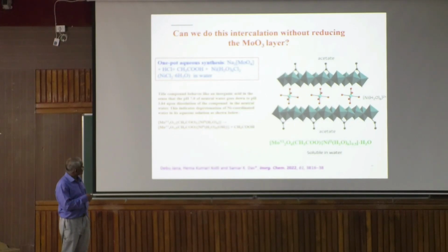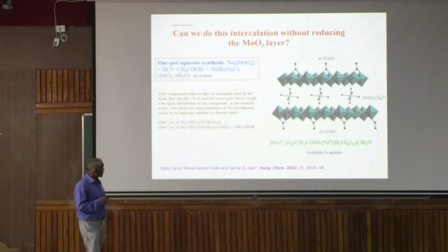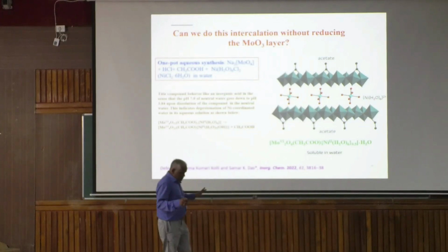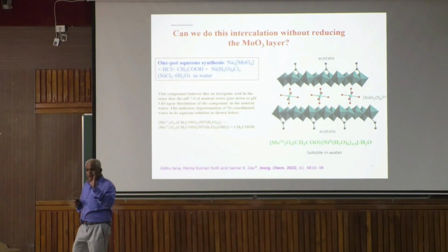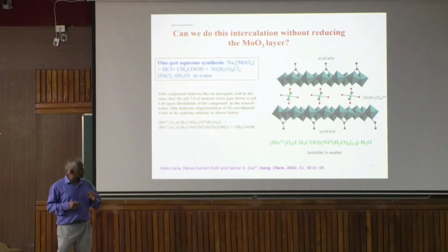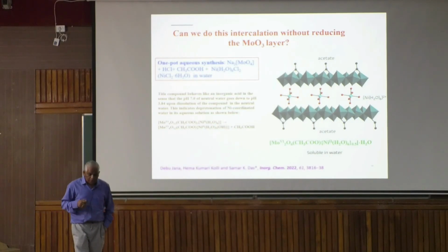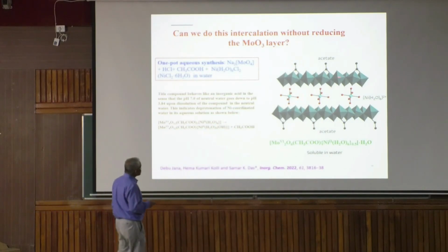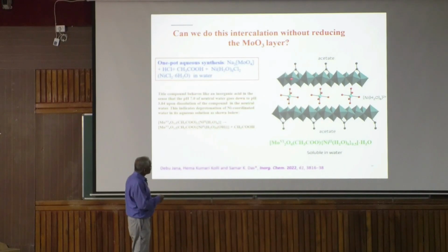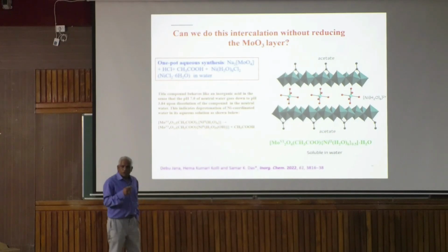Actually, if you put in water, that forms nickel hexaqua chloride. It's a covalent complex. So, just mix them together. Within 6 hours, you can get nice brown color crystals, and the crystal, we solved the structure, we found out that MoO3 in between nickel aqua complex, and it is not molybdenum bronze, by the way, because they are not reduced.